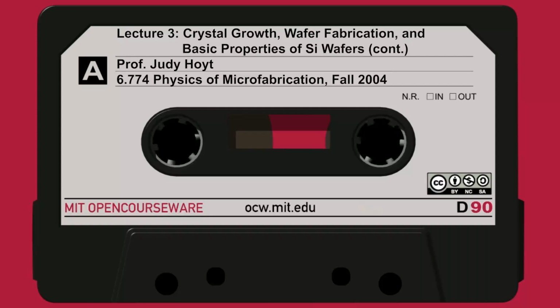For the purpose of this class, for modeling processes, there are 2 types of defects. We think of the I type, the interstitial type. Exactly how it's configured, we're not sure. We'll just use the symbol I, capital I, to refer to an excess silicon atom. And these point defects, V and I, turn out to play a really fundamental role in a lot of processes. They control diffusion. When we get to chapters 7 and 8, we'll be talking about diffusion. Extremely important. In oxidation, point defects play a very important role, as well as in activating dopants.